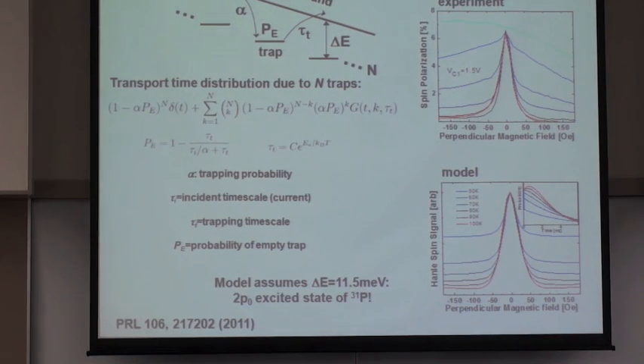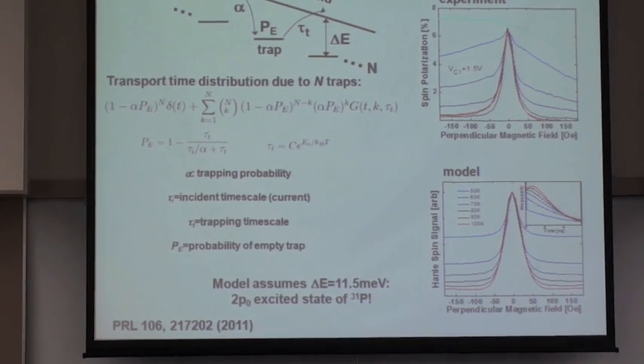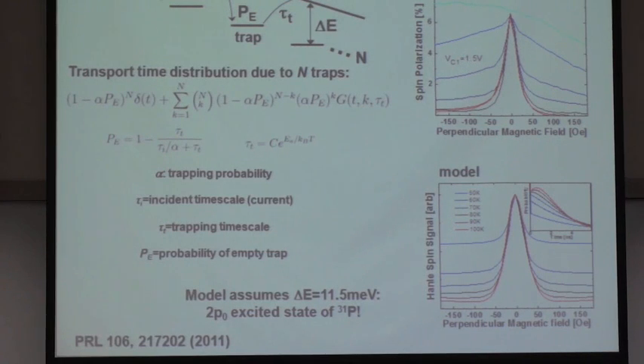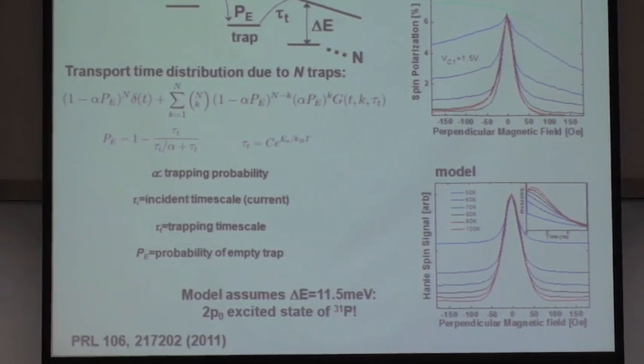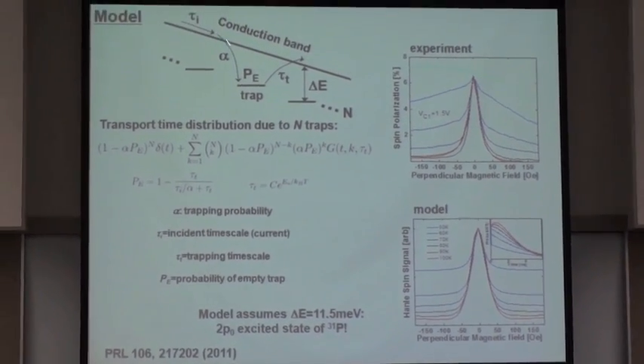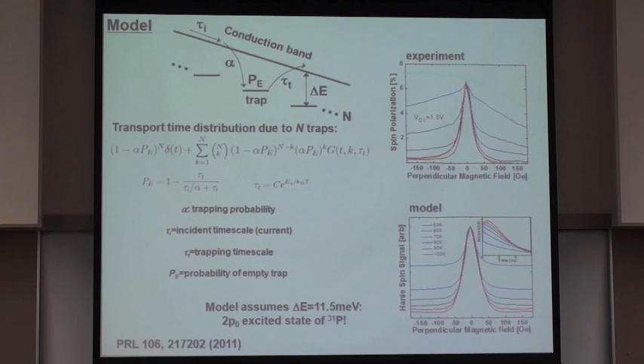Now, this part, I think, is perhaps most relevant to some of the work that you're doing here, simply because it naturally brings up the question of whether there's an interaction not only between the electrons in the conduction band states and the impurity traps, but also a natural interaction between electron spins that are filling the conduction band states and the neutralized donor, which is holding for a very short period of time spin polarized electrons in a localized state. Perhaps even there's an interaction between the spin polarized electron in the impurity and the nuclear spin of the phosphorus as well. But these sorts of questions, I think, have to be answered in the context of electron spin resonance and are very difficult and perhaps even impossible to probe using the transport experiments that I've described here.